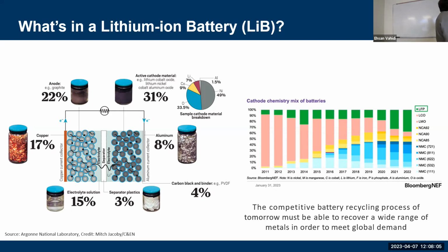Okay, so you can see the main metals here: copper, aluminum, lithium cobalt oxide, lithium nickel, manganese. And we see that over the years, the NMC nickel cobalt manganese chemistry has evolved, but initially a lot of the work was in the lithium cobalt sector, which I'll talk about a little bit later as to why.